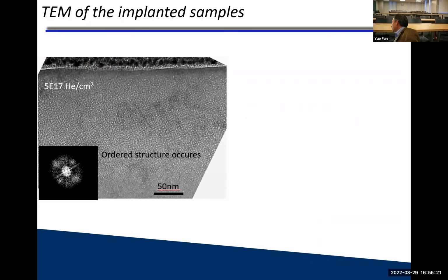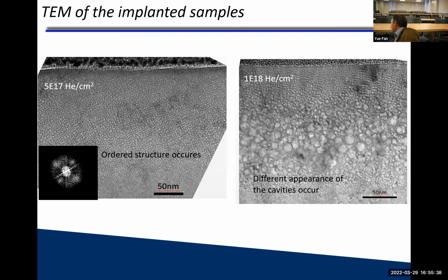And then in the TEM, what we see is beautiful helium bubbles building up in the material. In this instance, we see an ordered structure of helium bubbles. At this dose, the fast Fourier transformation shows us peaks, so there's an order to these things. But if you go too high in dose, you lose that order, and it looks a little bit more like bubble bath. And so you have just too much helium gas in that instance.